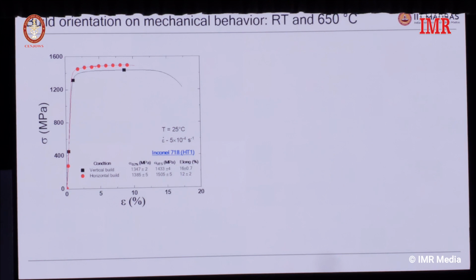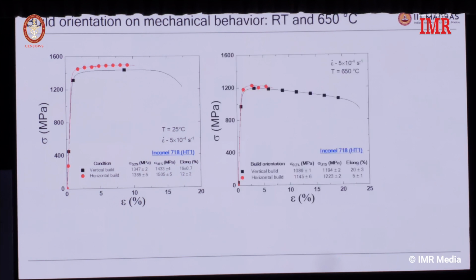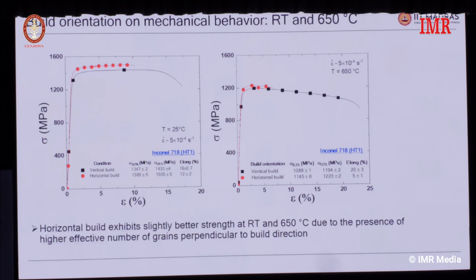So now the purpose is to find out whether we can get better properties. Here I have done the vertical build as well as the horizontal build. Now I have tested them on the vertical build samples as well as the horizontal build samples, because ideally I would like to see that if I print it vertically, horizontally or at a 45-degree angle, I should get similar properties. If you look here, the one built by the vertical build shows a higher elongation, but the horizontal build one gives the higher strength. So with the horizontal one, you are not getting the elongation, both at high temperature as well as room temperature.